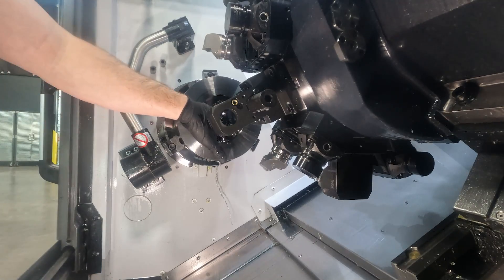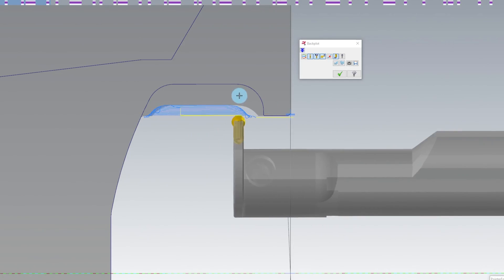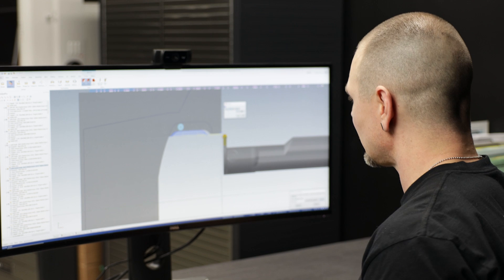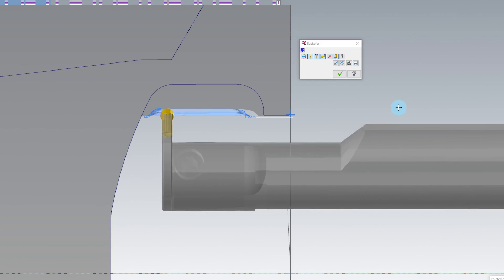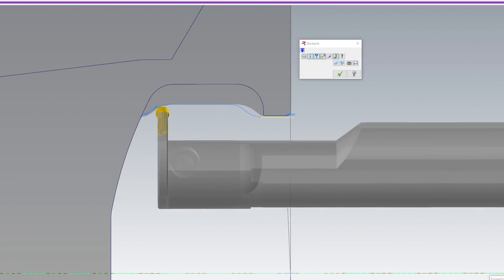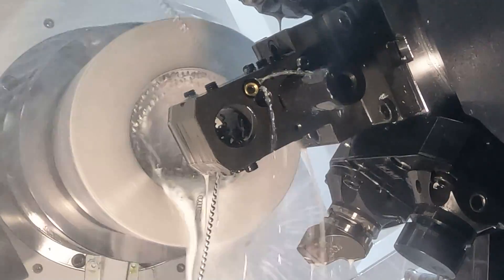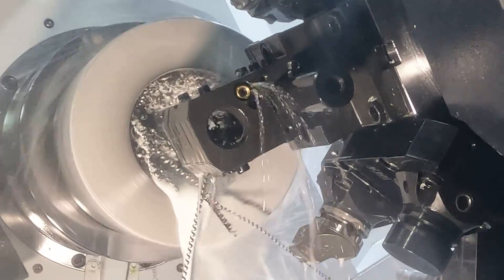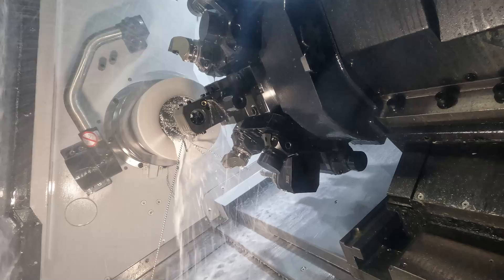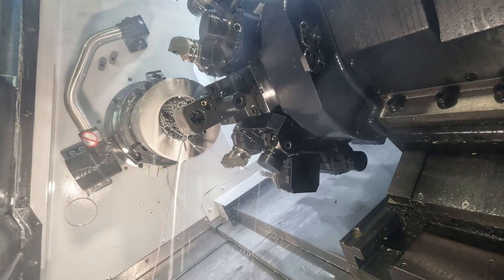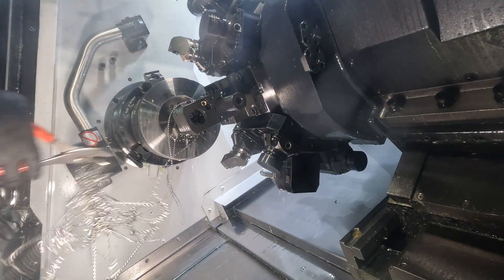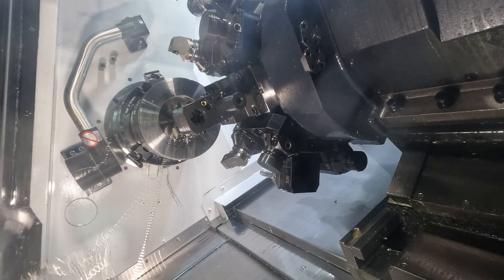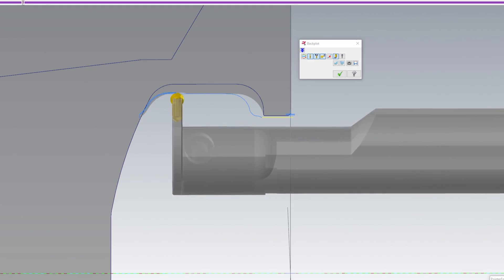Now again we had mentioned that the 15-5 was a little hard to break a chip. As you can see we get chips really kind of built up in here, so what I did is I actually broke this up into three different passes. You can see here's the first pass here, and here would be the second pass. Now what I'm doing is each time this stops and it comes up, the machine stops, allows me to get in and clear out any chips that might be interfering with coolant delivery, which will lead to premature tool failure, and I'll run the third pass.